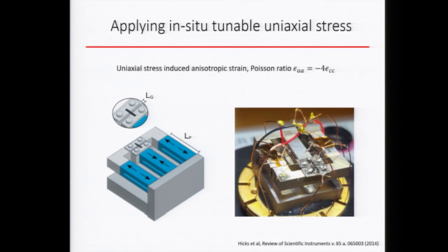Now, this is not isotropic pressure, right? You're actually pulling the crystal along one direction. For a natural material, when you do that, you'll expect a contraction along the other direction. For this particular material, it has a Poisson ratio of about 1 to 4. So when you're pulling along, let's say, the A lattice constant, you're shrinking along the C lattice constant by only 25%.